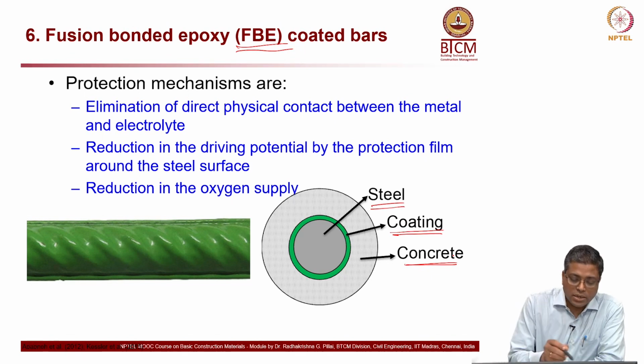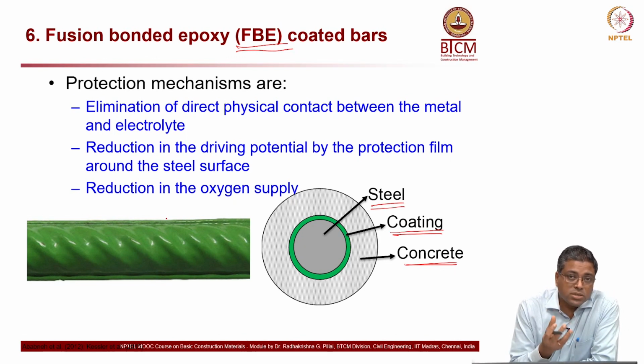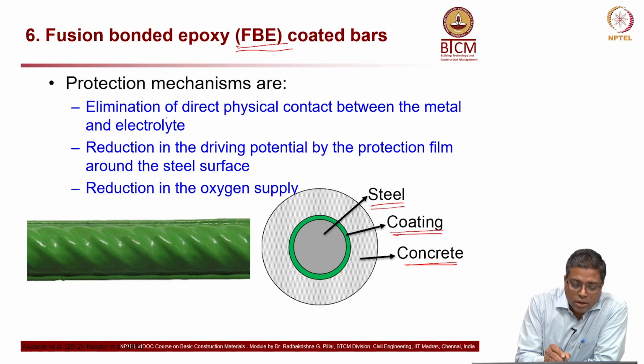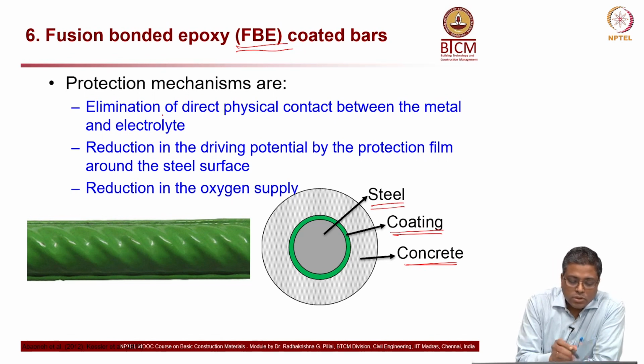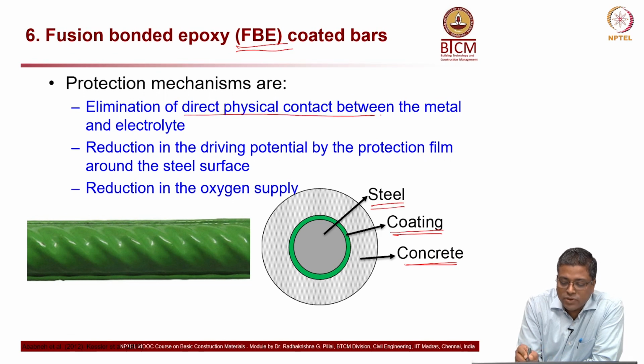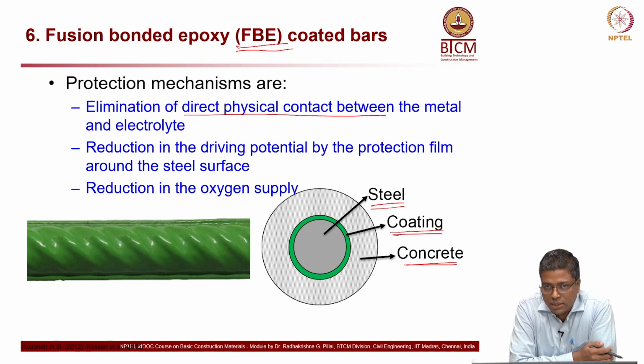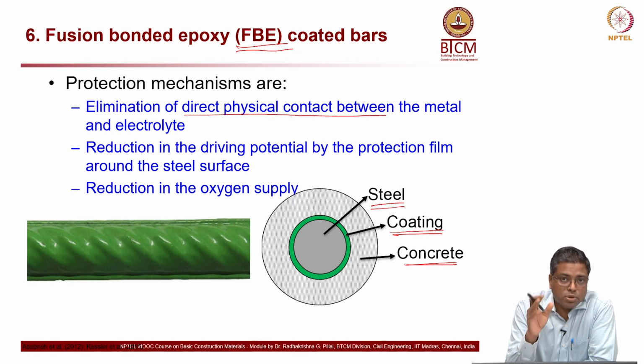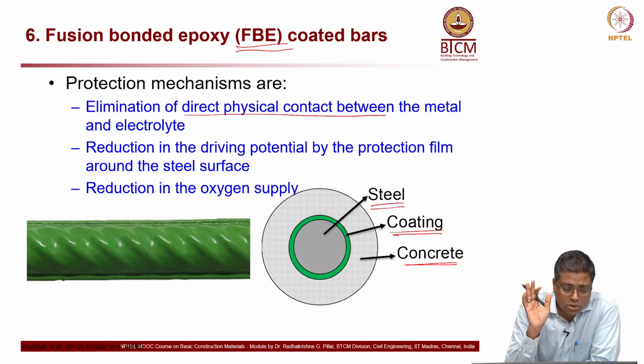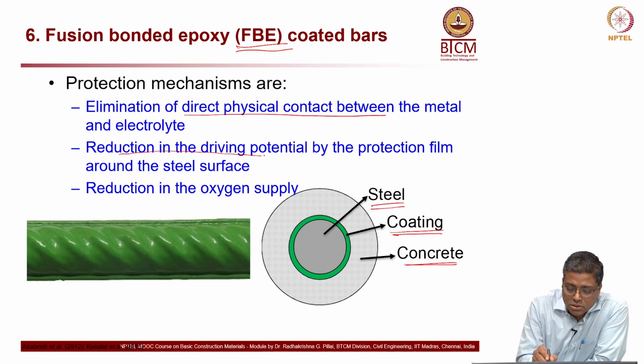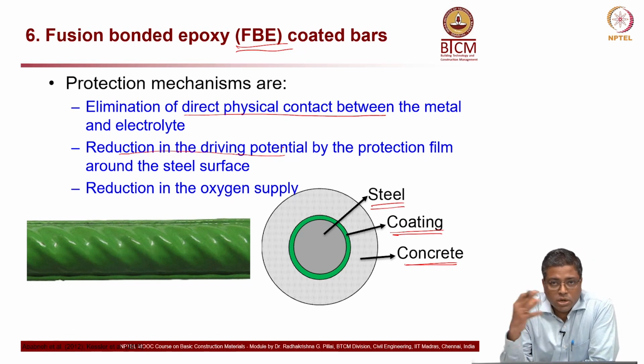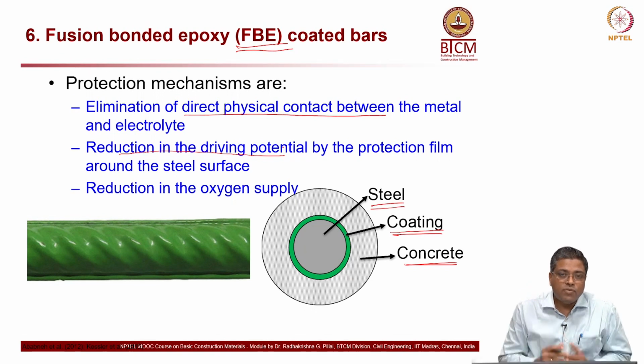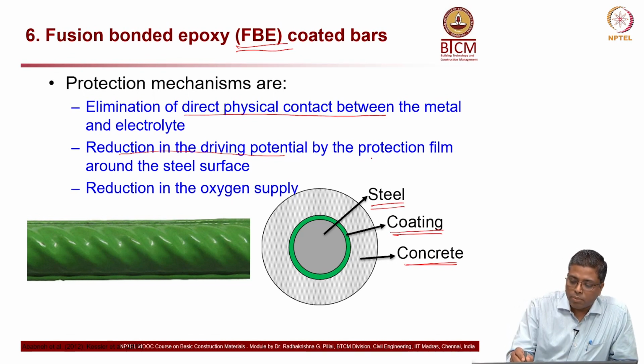Now, what the protection mechanism is: this epoxy coating, it is not painting, it is coating. Okay. There is a little difference between painting and coating. So, this coating actually eliminates direct physical contact between the metal, the steel, and the electrolyte, which is the concrete. So, there is supposed to be no connection between the steel and the concrete if it is a very good quality epoxy coating. Then it also reduces the potential difference, which is the driving force for the corrosion reaction to happen. So, there is a protection.